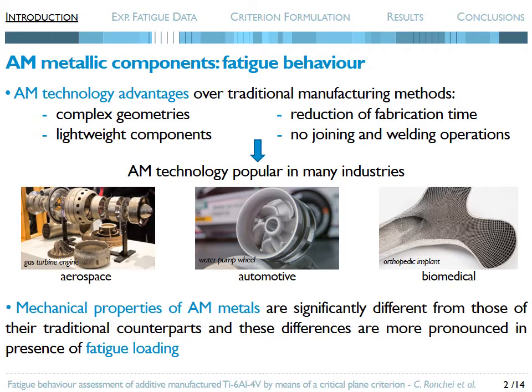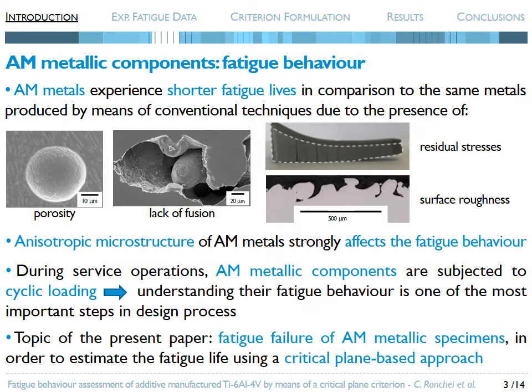As is well known, the mechanical properties of AM metals are significantly different from those of their traditional counterparts, and these differences are more pronounced in presence of fatigue loading. In particular, AM metals experience shorter fatigue lives in comparison to the same metals produced by means of conventional techniques, due to the presence of both internal defects, porosity and lack of fusion, residual stresses, and high surface roughness, which are material inherent features deriving from the manufacturing process.